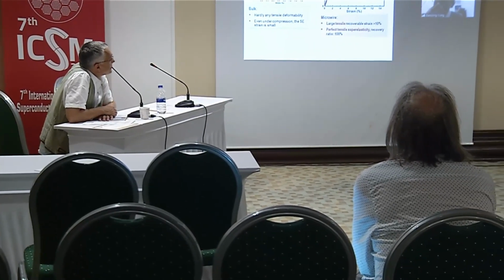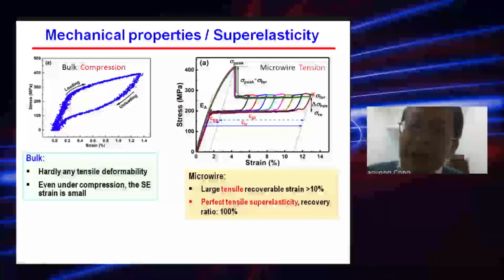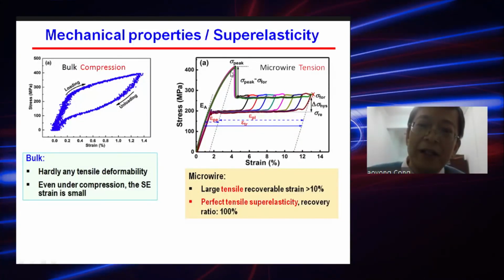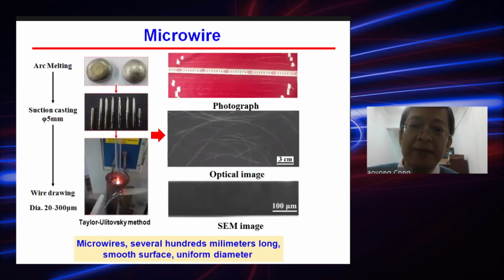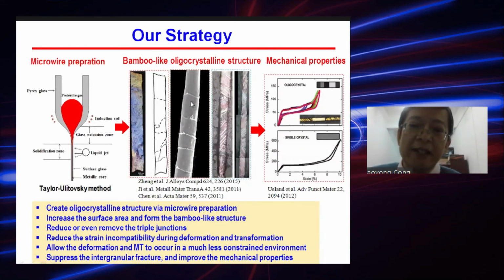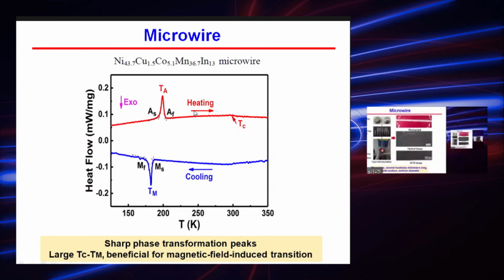I think in this kind of microwire, when you want to nucleate martensite, its energy barrier is very large. You need a large stress to nucleate martensite. Once it's nucleated, you don't need such a large stress, and it can propagate very easily. This may be because in the microwire we don't have many grain boundaries, and the microstructure is homogeneous. So there are quite few defects which can facilitate the nucleation.